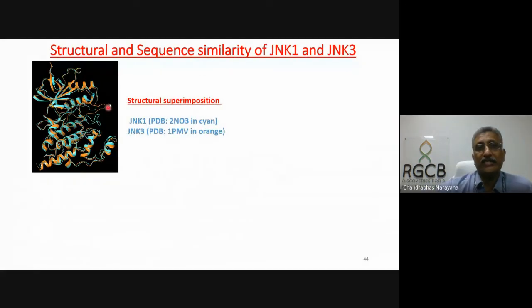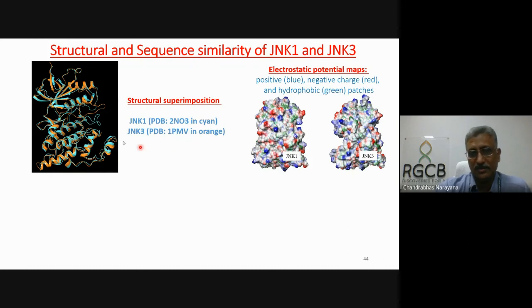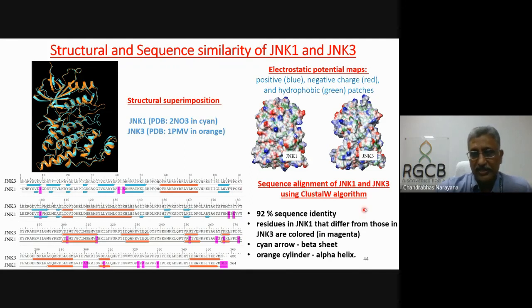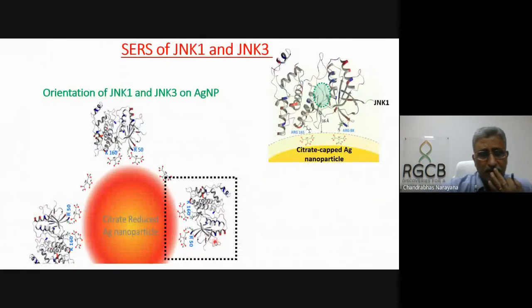If you look at the structures of JNK1 and JNK3 and superimpose the two, you can see very little difference between the two. They are 92% similar. You can see that the electrostatic map also looks very similar, but there are differences in the electrostatic. Here is the sequence alignment. You can see 92% sequence identity, but the differences are in the alpha helices and beta sheets, where single residue changes are happening in the system. Those are the things which make them different. Otherwise, they both are identical.